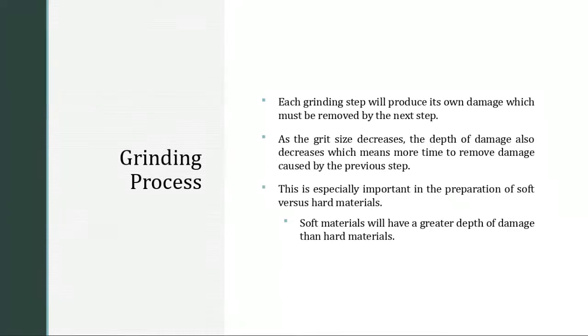Each one of the grinding steps will create its own damage layer. That's why after sectioning the sample, if you were to hacksaw, you have to start off with a 120 or 180 grit. If you used an abrasive cutoff wheel, you could probably start off with a 240 grit. And if you sectioned your sample with the precision diamond blade, which would put the minimal amount of damage, you could probably start that step off at 600 grit for your start point in the grinding process.